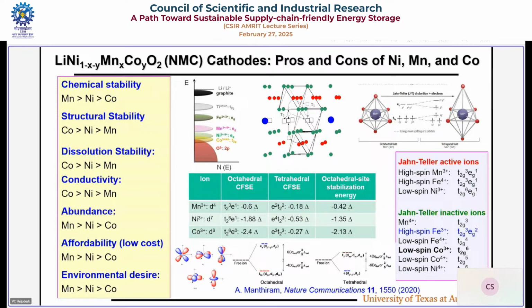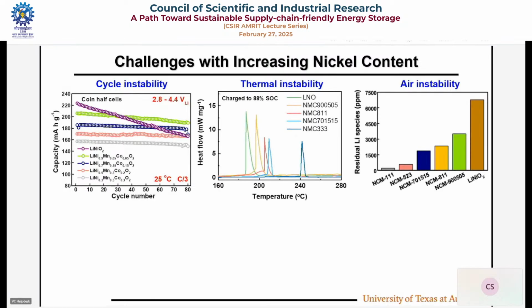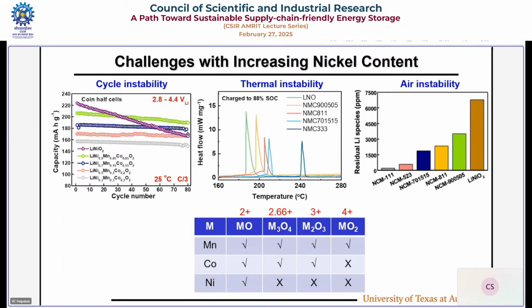In all of them, nickel is in between, that's why all the action is on nickel. You take any company, Tesla, Samsung, LG, everybody wants to increase the nickel content. Now with the nickel, 3 problems. 1, when you increase nickel, you get higher capacity, but it fades. Cyclability is poor. My battery doesn't work long. That's cycle instability. I also have the thermal stability decrease. That means it loses oxygen at a lower temperature, safety problem.